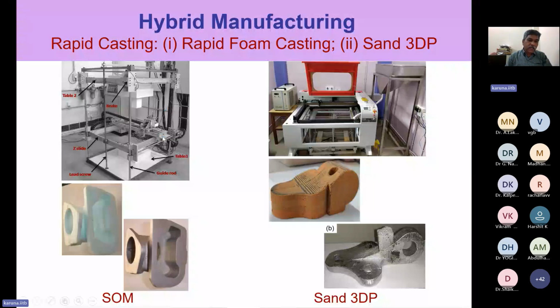Now you see this entire part is produced out of just 3 slices. So you can see the kind of layer thickness on it. They are sometimes as big as 2 inches in layer thickness. It's a beautiful machine. So using the thermocol or foam pattern as pattern, similar to investment casting, we can produce a metal part. So this foam pattern was made on this machine. Using this foam pattern, we produce this metal casting. This is related to rapid casting.